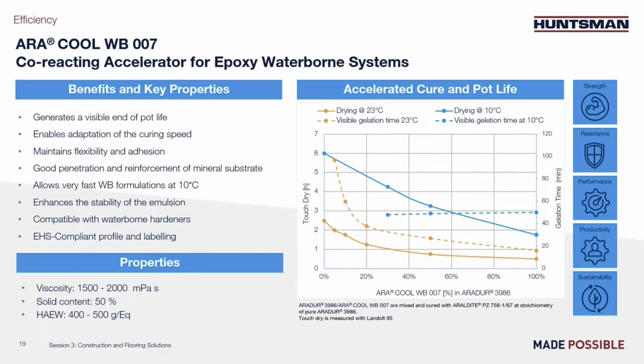The system Aradur 3986 PZ756-1 has no visible end of pot life. And you can see that with 5% substitution of the hardener, it allows already the visible end of pot life, which is really positive for a waterborne system because it avoids the mistake of the applicator. The acceleration is really visible at 10 degrees, from 6 hours down to 2 hours if you would use the accelerator 100%. At 10 degrees, you get a visible end of pot life at either 30% substitution or 100%.